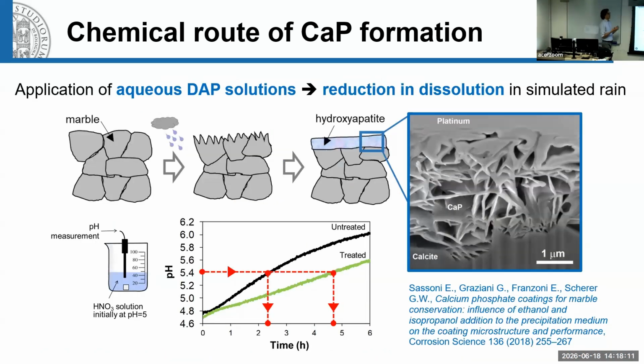What can we do with this? Again, the first function that we studied was developing a protective layer, a barrier to reduce the solubility of the substrate. Here in this graph, you can see some easy tests that people do in the lab to check whether this barrier is providing protection to the substrate. So this is a small piece of marble. I put it in a solution with a slightly acidic pH to simulate rain, and then I measure the pH change over time. Why does pH change? Because this rain or acid rain is corroding the marble.